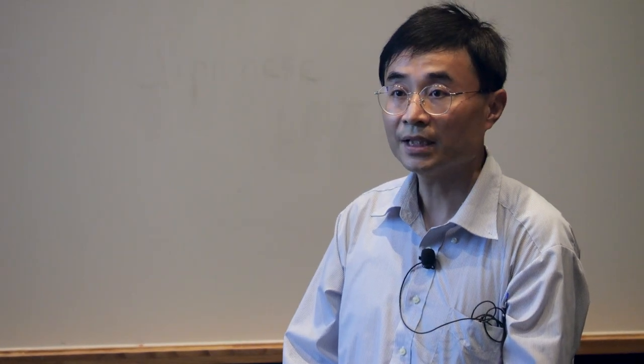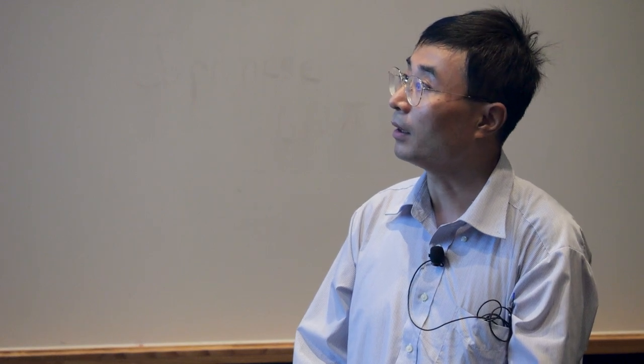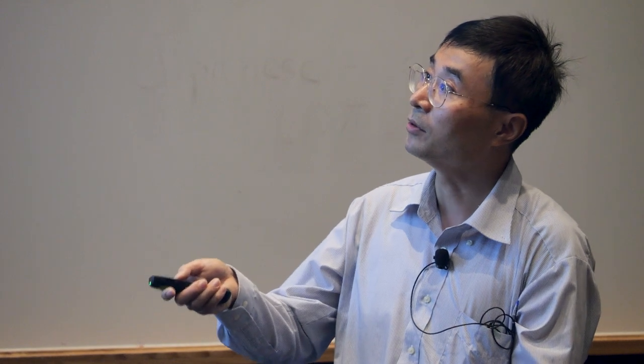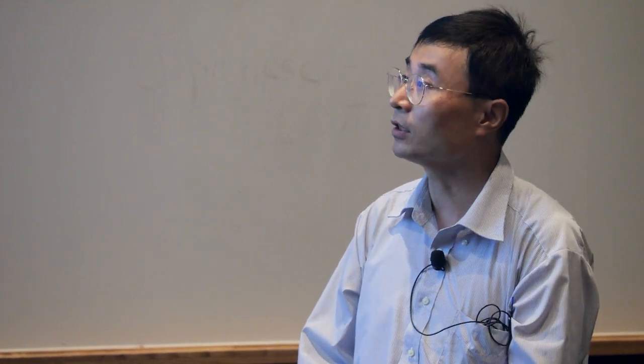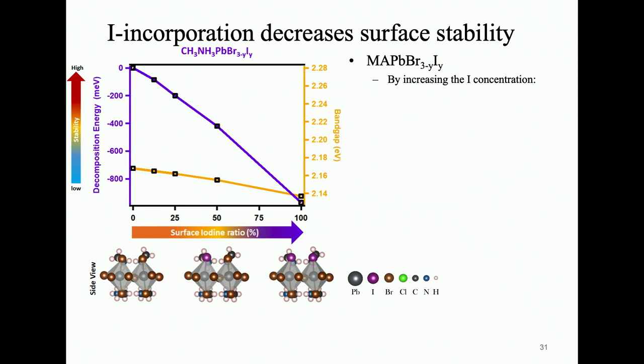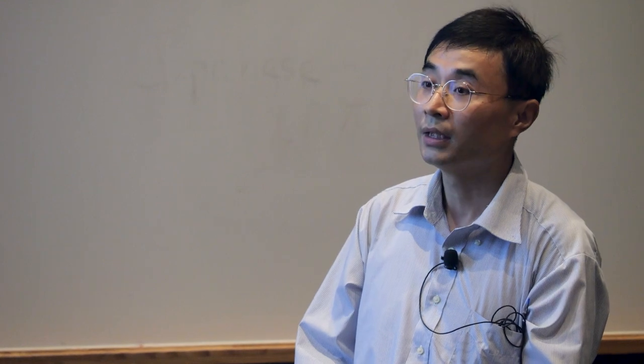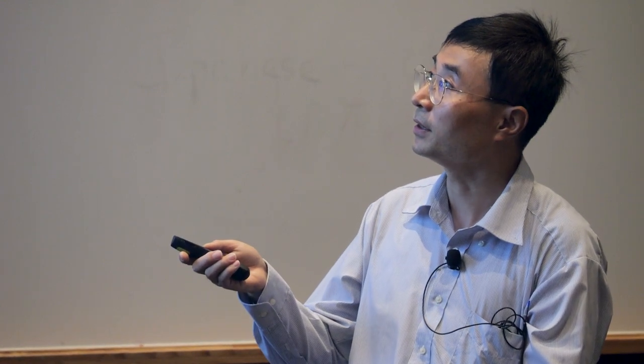To further understand the impact of the halide mixing, our collaborators also calculated the decomposition energy, which is an indicator for material stability. In the case of incorporating iodine ions into the MAPbBr3 surface, we found that the surface stability decreases monotonically as the surface iodine ratio increases. This suggests that incorporation of iodine ions on the surface of MAPbBr3 decreases the surface stability.